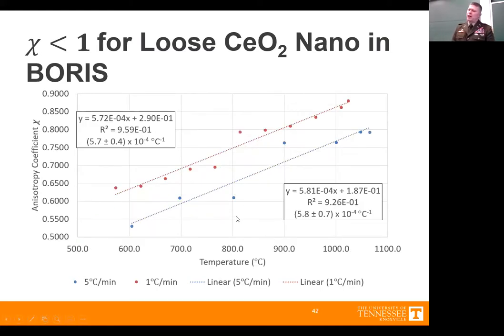Here they are plotted, with chi on the y-axis, that is delta R over delta A, versus temperature. What this is showing is that the slopes of the sintering processes were very similar for both heat rates. It didn't really matter which heat rate was used, and I saw the same for 10 degrees and in between heat rates. The slope of the data set didn't significantly change. However, the onset of sintering was delayed. It started at a higher temperature when I used a faster heat rate.